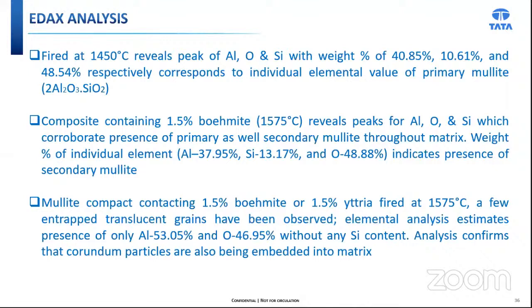So we have observed the presence of cristobalite, we have observed the primary mullite, we have observed the secondary mullite. Also, in mullite compact containing 1.5% boehmite or 1.5% yttria, the presence of elemental corundum particles is also observed.